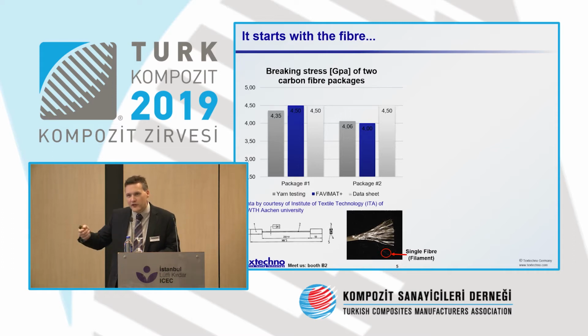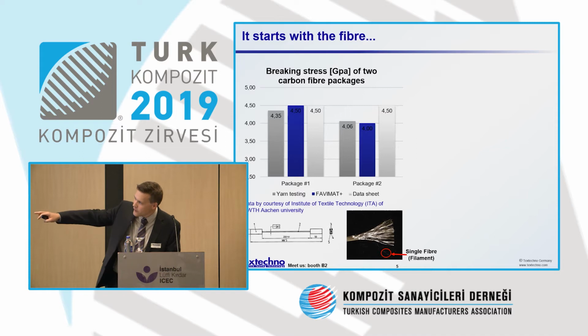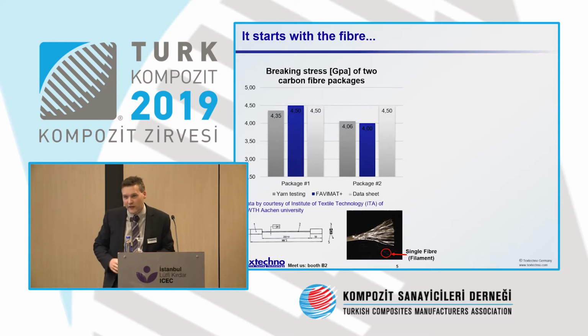And then you start measuring the tensile strength, and it's supposed to be 4.5 gigapascal. But it actually, on the left-hand side, these bars, they indicate that for the first package on the left-hand side, you really match the vendor specification. But for the second package, you have a loss of about 10% of the total tensile strength in that package.